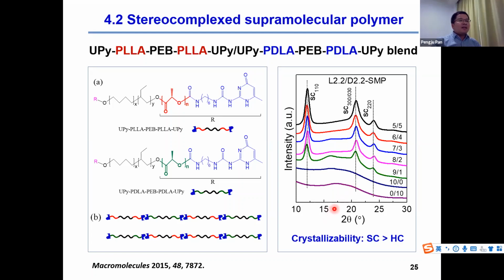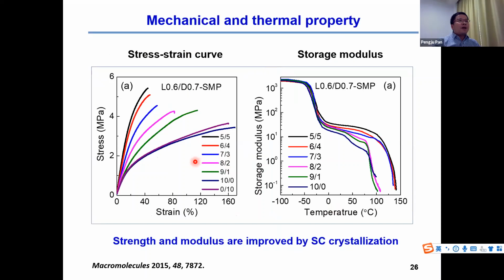The non-crystallizable material becomes a highly crystalline material after stereocomplex crystallization. Due to the effect of crystallinity, stereocomplex crystallization has a remarkable effect on the mechanical and thermal properties of the supramolecular polymer. The stress-strain curve and the DMA curve show the strength, modulus, and softening temperature improve with the crystallinity of stereocomplex crystallization. However, the polymer will become more brittle and its fracture strain decreases after stereocomplex crystallization.